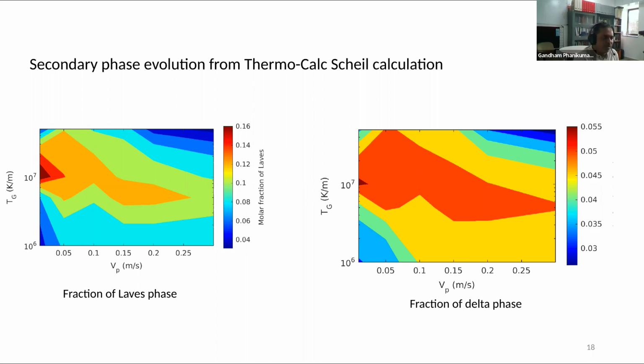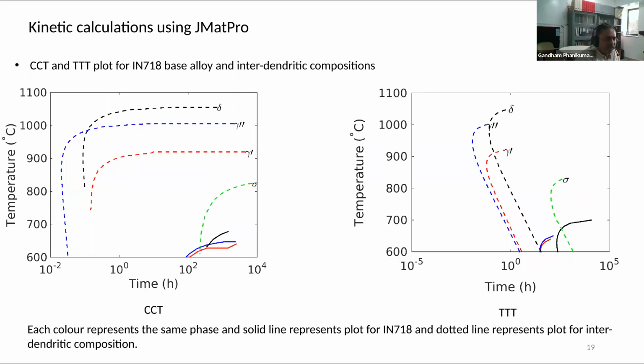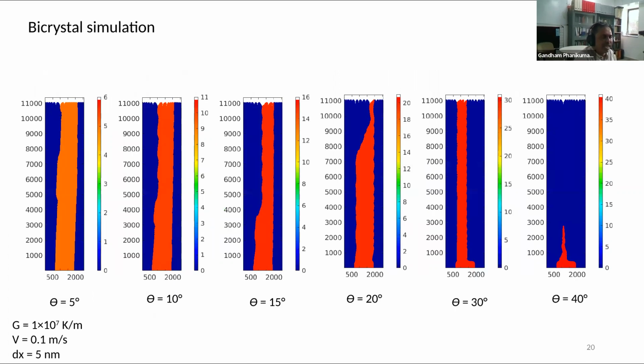So Mohan's work has shown that there's a relation between the processing conditions and the detrimental phases that may form in the additive manufacturing scenario. So the gradient values we have explored are relevant for additive manufacturing. Okay, and we can also then go on to predict the kinetics of phase formation, because these can be calculated. And when we do that, we are able to show that certain phase formations have a fairly leftward curve, which means that their probability of formation is high. Okay, so those are the kinetics we can do.